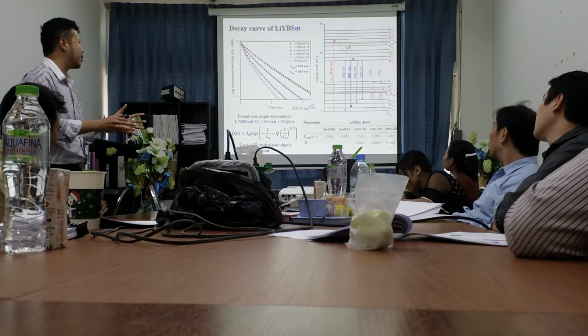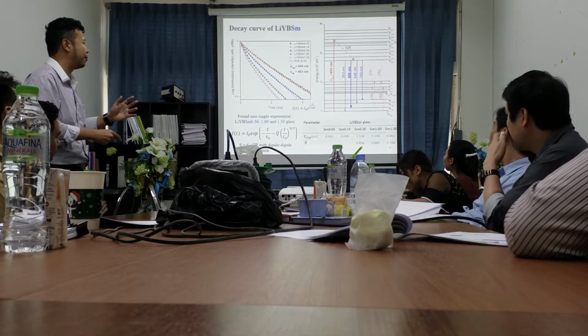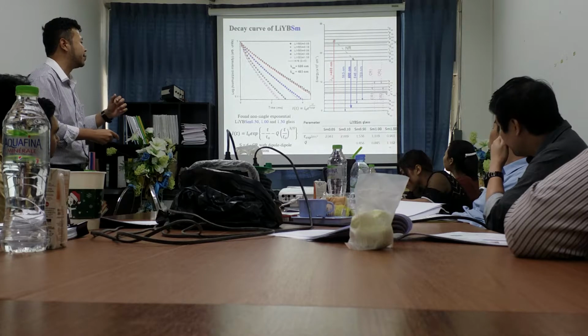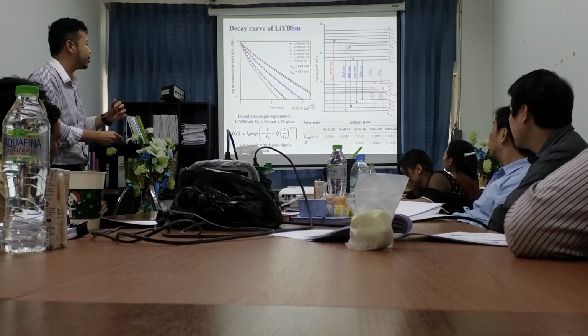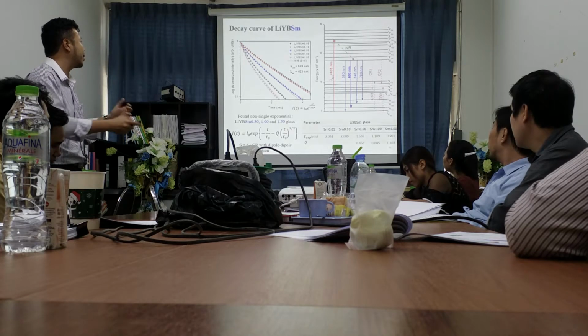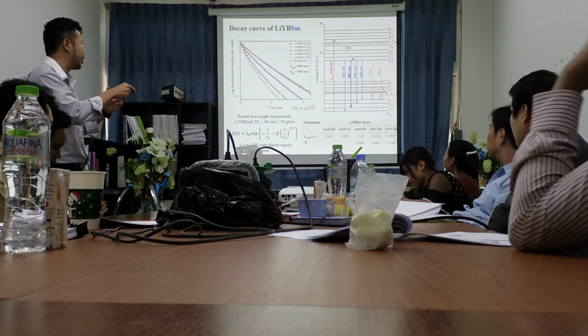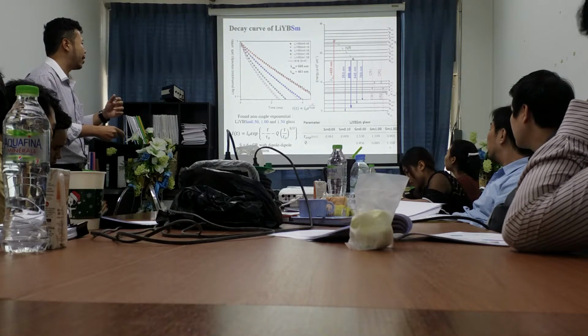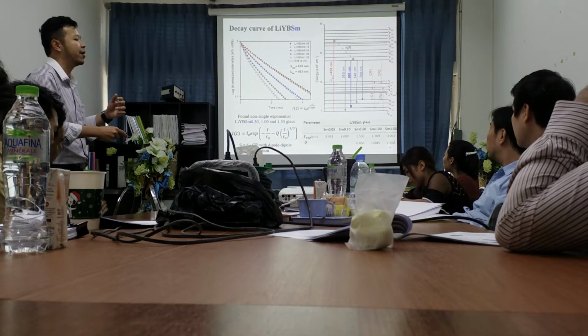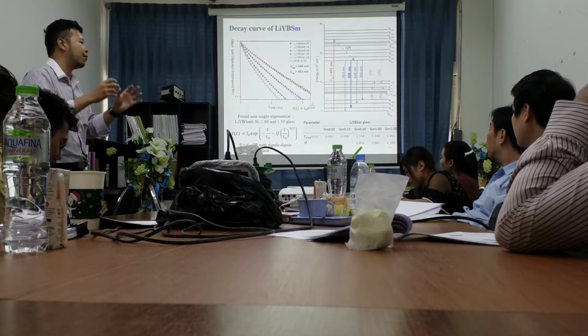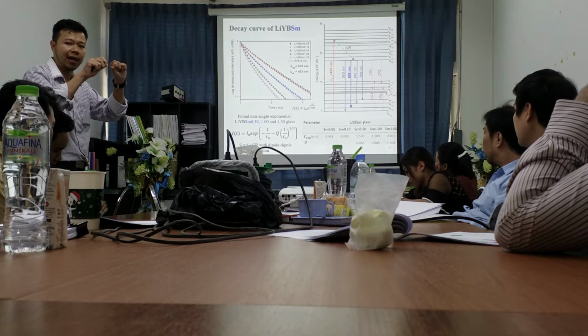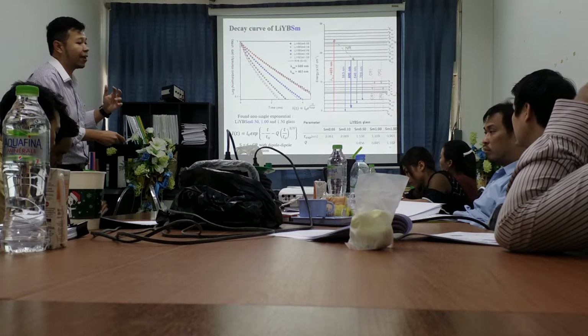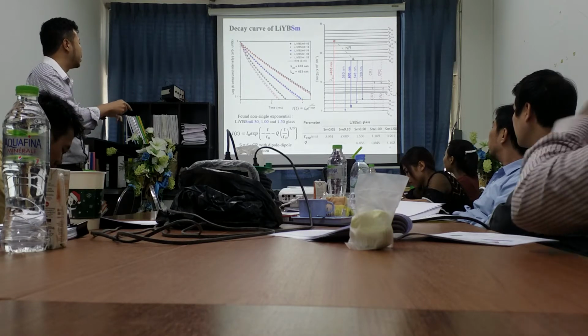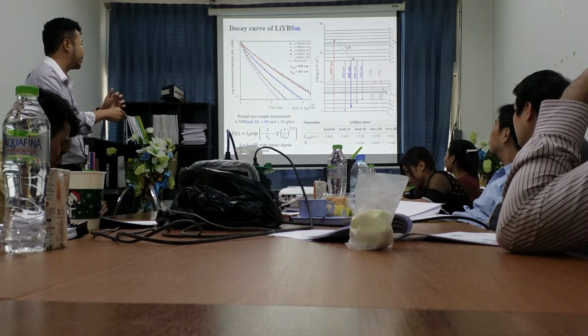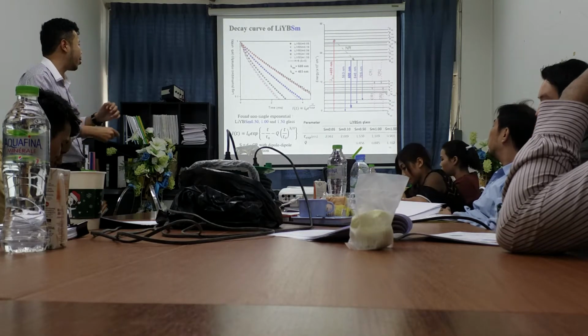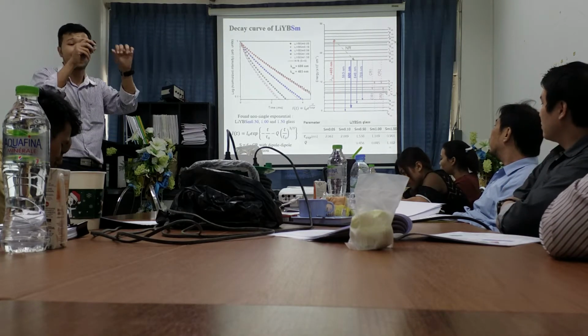Decay curve. The first one is I measured the lifetime and found the lifetime of this glass is in the millisecond range. And the lifetime decreases with increasing samarium oxide concentration, combined with a non-single exponential in the decay curve. I fit it with the IH model and found Q increases with increasing samarium oxide in the glass matrix. That means more samarium oxide makes energy transfer easier and it drops down the luminescent lifetime in the glass. Also, for fitting, S shows the best fit at 6. That means the energy transfer is a type of dipole interaction between the samarium ions.